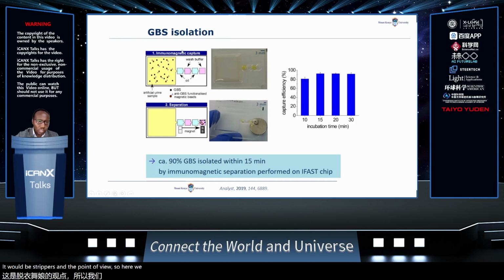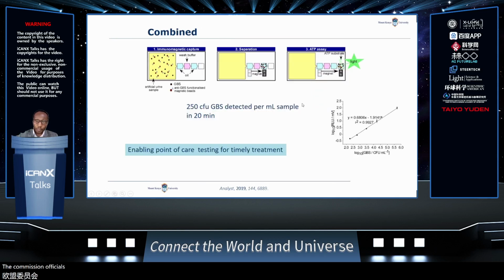So here, in the first image, we are using the immunomagnetic capture, where we use anti-GBS functionalized magnetic beads to bind onto antigen on the surface of the group B streptococcus and subsequently be moved, using magnetic force through a magnet, to the last chamber, from where we can do the ATP assay and then be able to quantify or detect the infection. So using this, we were able to isolate 90% of group B streptococcus within 15 minutes. Any more time that we added onto this did not seem to improve the capture efficiency. So when we combined the iFast and the ATP assay, we were able to achieve a detection of 250 colony-forming units of group B streptococcus per mil sample in 20 minutes total, enabling point-of-care testing for timely treatment.